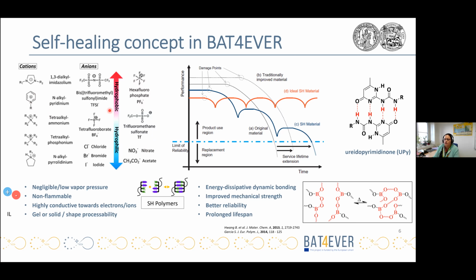The role of the ionic group is, of course, to enhance the ionic conductivity of the materials, whereas the polymer fraction should give the distinct mechanical stability to the desired material. In order to achieve the self-healing functionality, we can also add additional self-healing groups, either supramolecular groups, for example, like here, the quadruple hydrogen bonding UP group, or we can go to the dynamical covalent bonding and introduce, for example, boric ester linkage into the polymeric material to achieve the desired self-healing.